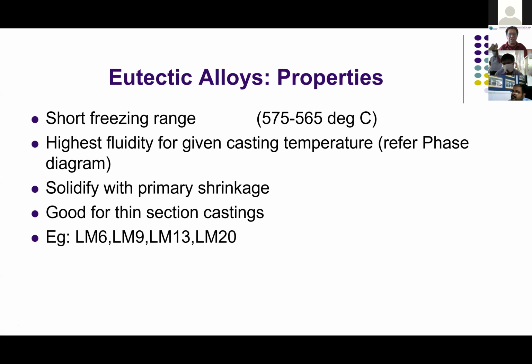The alloy which freezes in a very short range gives a very good casting quality, very little shrinkage, and also dispersed shrinkage. It solidifies with the primary shrinkage, good for thin castings. Since the fluidity is extremely high, you can go for a very thin casting. LM6, LM9. LM9 is more or less like LM6. LM9 also has a small quantity of magnesium. Sometimes they add copper also. LM13, yes, we add a little bit of nickel here, and LM20.